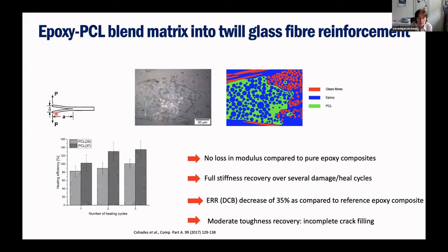And then with the DCB test, in terms of the stiffness of the first DCB curve, we had not much loss compared to pure epoxy. Of course, the fibers dominate. We had a full stiffness recovery for several damage and heal cycles. We had, however, a quite decreased energy release rate, so the G1C of the material, compared to reference epoxy composites. It was 35% less than the normal epoxy. And we had a moderate toughness recovery, due to this incomplete crack fill.